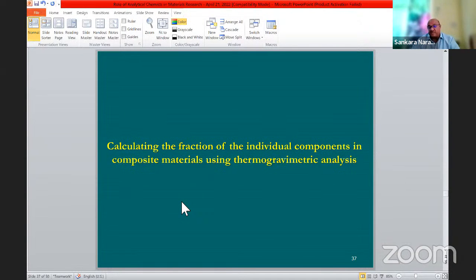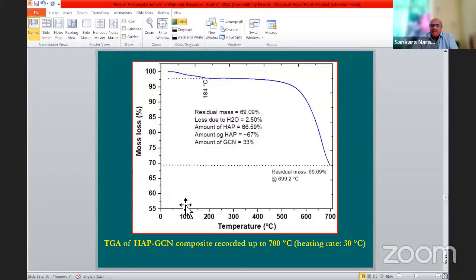So how can an analytical technique be effectively used? We did TGA and recorded up to 700 degrees centigrade at a heating rate of 30 degrees. The residual mass is about 69% up to 700 degrees. We know that hydroxyapatite is highly thermally stable, but the graphitic carbon nitride starts to decompose at about 600 degrees centigrade, and when reaching 700, it completely decomposes. So we ran the TGA curve to 700 degrees centigrade.